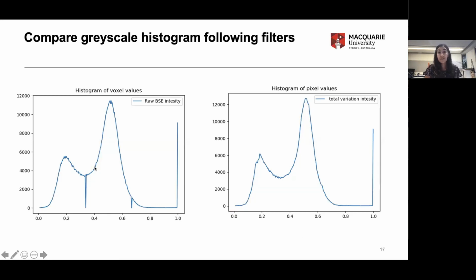So following the grayscale filtering, we can see that this hugely improves and smooths that histogram of grayscale intensities. What's really nice about working with SEM images and indeed grains in SEM photographs is that you usually end up with a bimodal grayscale distribution. And that's exactly what you can see here. There are 2 different peaks in grayscale intensity, one of which correlates to that background orthopyroxene, which we're not too interested in measuring for this example. And this peak here corresponds to those bright spinel grains, which we should be able to measure.